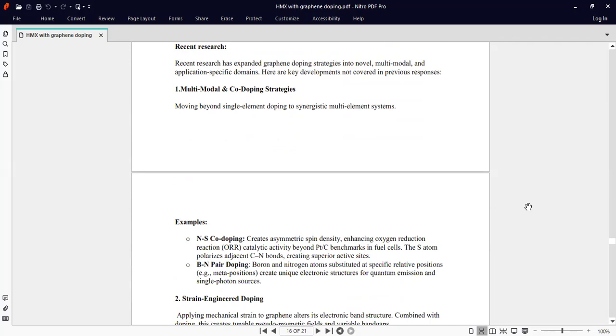Recent research has expanded graphene doping strategies into novel, multi-modal, and application-specific areas. The other key factors for doping which will be discussed are as follows. Multi-modal and co-doping strategies: moving beyond single element doping to synergistic multi-element systems. An example is nitrogen-sulfur co-doping, which creates asymmetric spin density, enhancing oxygen reduction reaction (ORR) catalytic activity beyond the platinum-carbon benchmark in fuel cells. The sulfur atoms polarize the adjacent carbon-nitrogen bond, creating superior active sites.